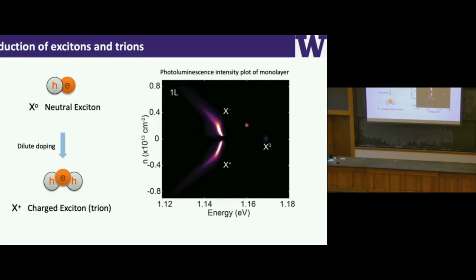We can do a bit more measurements. For example, here I show you the intensity plot of these photoluminescence measurements. The vertical axis is doping, the horizontal is the energy of my photons, and positive means electron doped, and negative means hole doped. From this plot, you will see that at charge neutrality, we have a neutral exciton here with these little weak features. And as I start to dope the system, I see that the negatively charged trion or positively charged trion appears. So that's another way we know that the system is doped: we have a neutral exciton, and we have a charged exciton, or trions.